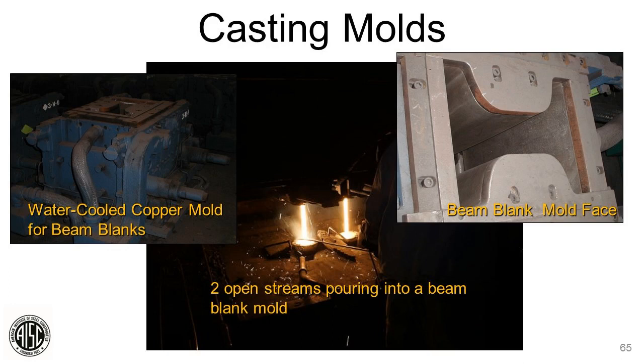And we call it open pour because you can see the stream of steel coming through. And there are collector nozzles on top of the mold. That's what you see, the little refractory dishes there on the top. And they seal the liquid steel as it goes into the mold, and there's mold powder inside that to keep the air from that steel in the mold. Next slide, please.